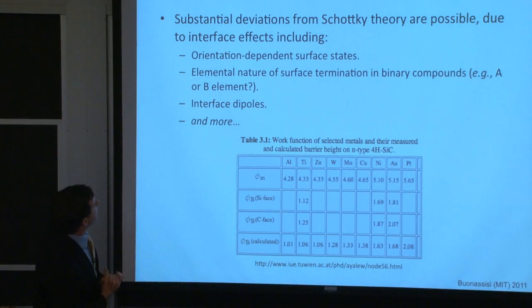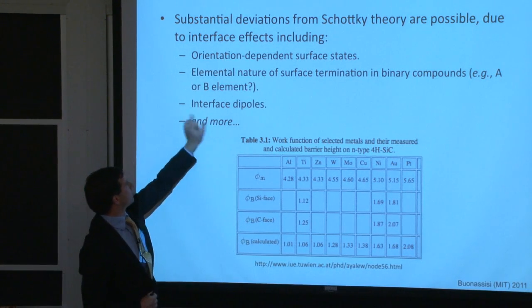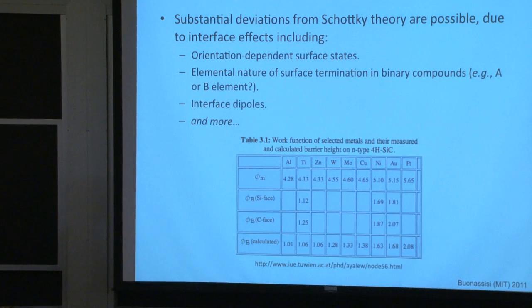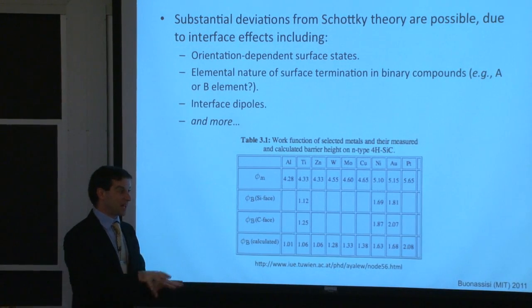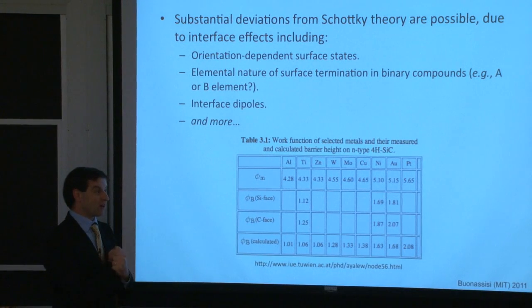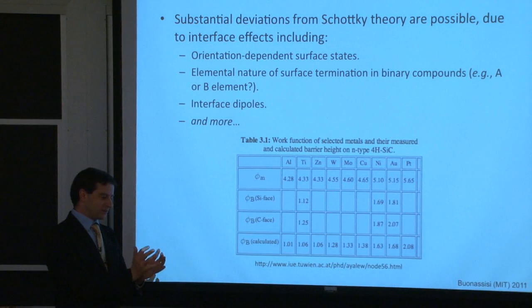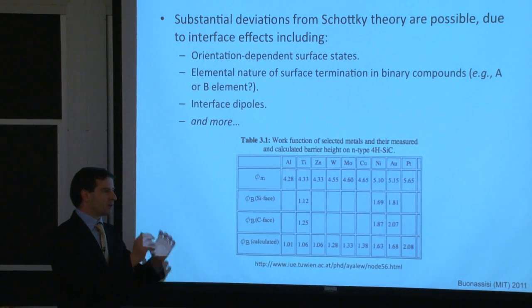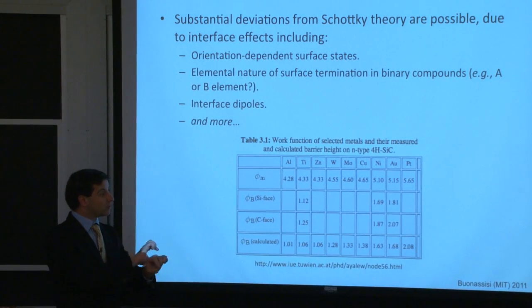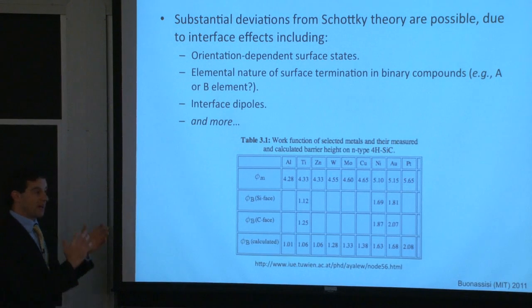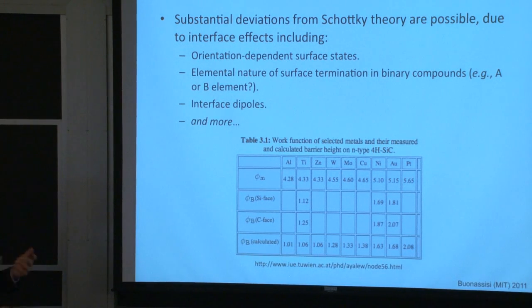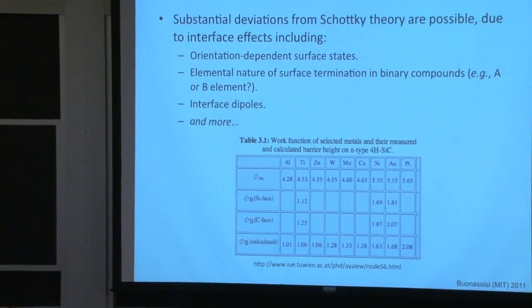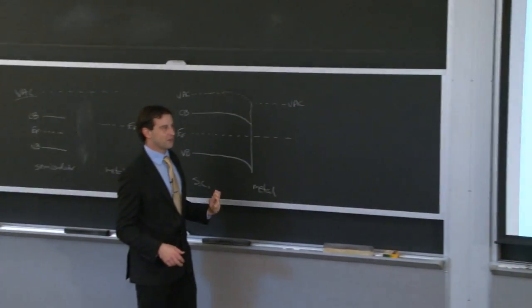And finally, interface dipoles. This relates back up to the first one in part. This just goes to say that if I have an ionic material or an element there at that interface that is grabbing charge, I could result in a small region of negative charge and positive charge forming a dipole right there at the interface. And if I have a buildup of charge, I have a field. If I have a field, I have a potential. And if I have a potential, I'm going to be disrupting this precise interface right here.